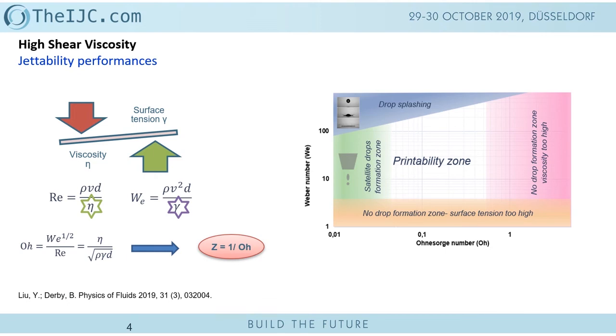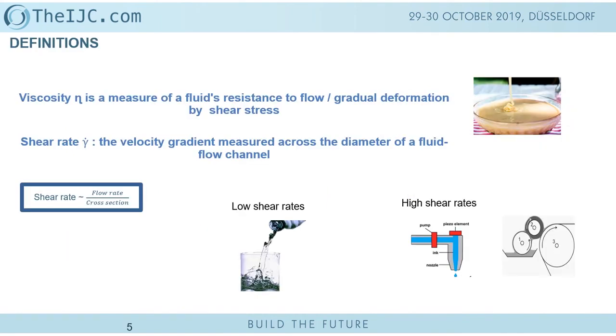Measurements are usually done with conventional geometry at lower shear rates. I will show examples of formulations that are assumed to be Newtonian but at higher shear rates show shear thinning profiles. To introduce it simply: viscosity is the resistance to flow. Shear rate is the velocity gradient measured across a section. A bigger cross section with a bigger flow rate generates a lower shear rate, while a lower cross section with high flow rates generates higher shear rates.